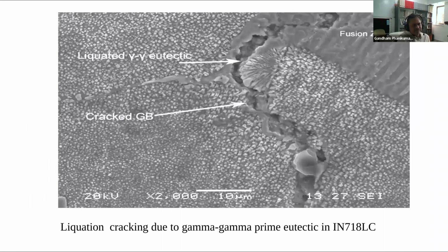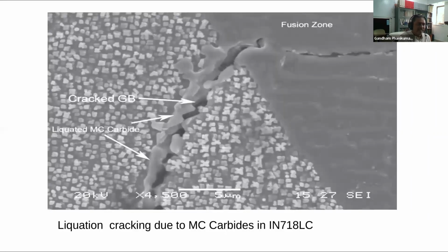Now, if you look at liquefaction cracking, the location of liquefaction cracks is slightly different. They will show you the eutectic formation nearby, and therefore you can make out that a liquefaction has happened. A eutectic has actually formed liquid during heating, and that liquid has gone around and created a crack. Liquefaction cracking because of eutectic formation can also happen because some of the carbides can form a eutectic with the matrix. Whenever you have chunky carbides in superalloys, you can have a eutectic between them, and that can also cause the liquefaction. So one has to be very wary. You may want the precipitates because you want the strength, but eventually that also should not lead to these problems.